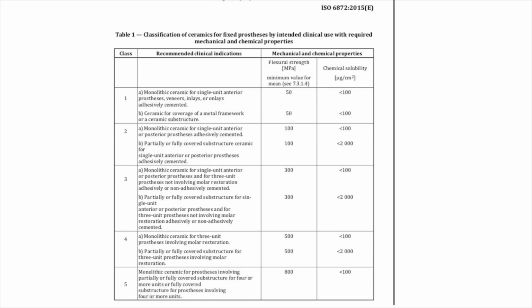And so when you look at the regular porcelain that you just put on porcelain fused to metal and things like that, they only have about a 50 megapascal strength. It's amazing that you have PFM crowns that have been in the mouth for 40 years with very, very little wear. They'll wear the hell out of the teeth, but they won't break. And it's because of a good metal framework underneath and proper firing. So you have to understand that the stress and the cooling have a lot to do with the success of veneering materials, and we'll get into that a little bit too.